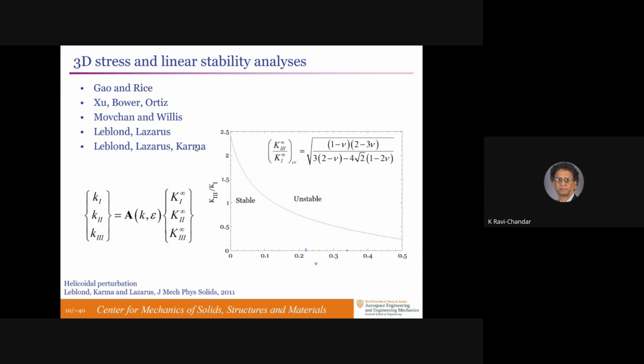And they found a criterion that if the global values of K1 were given, you can calculate the local values of K1, K2, K3, and put this into the energy release criterion and see if the amplitude of the things would grow or decrease. And we found a critical transition point that depended on the Poisson's ratio of the material. A bit suspect, but it's okay.